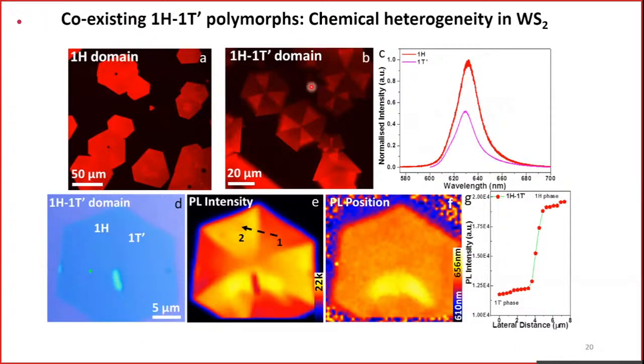Right? Then this is what I was talking about, the fluorescent microscope image. If it is only 1H semiconducting phase, you will have a uniform intensity across your flake. But when we have a biphasic, 1H and 1T prime, you have a varied intensity, and also spatially they are very nicely organized in the form of triangles. Then we are calling it 1T prime because the intensity in the PL is not zero. If it is 1T, it is metallic, you wouldn't get any signal. Since we are getting a signal of almost 50% or 40% of your semiconducting phase, we are thinking it is semi-metallic. In this case, it is not a zero band gap; there is a small amount of band gap. Rather than saying semi-metallic, we should say probably a very, very small semiconducting gap. That is what is promoting this kind of low intensity emission.